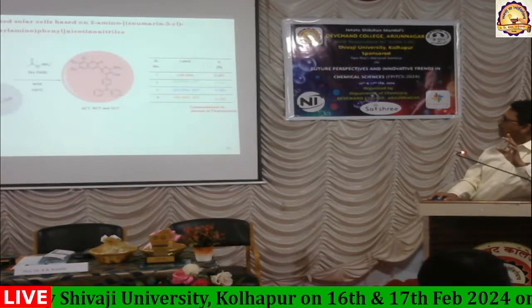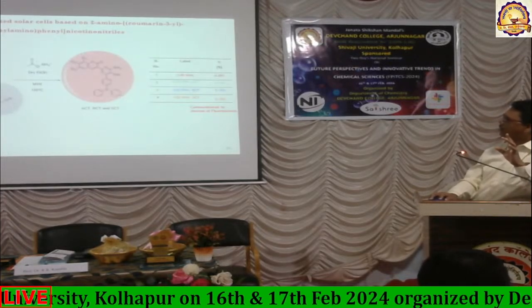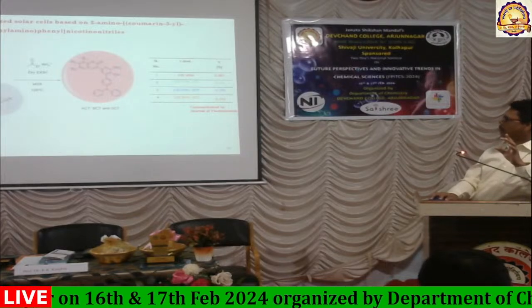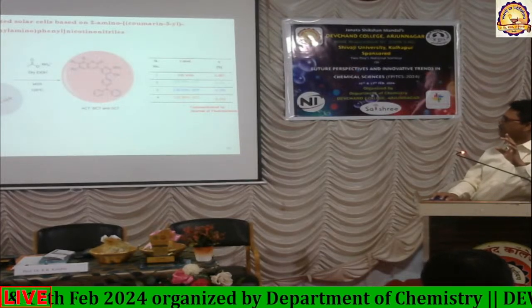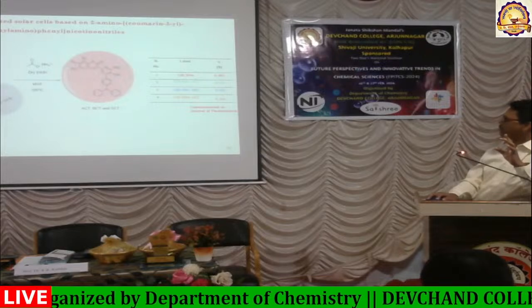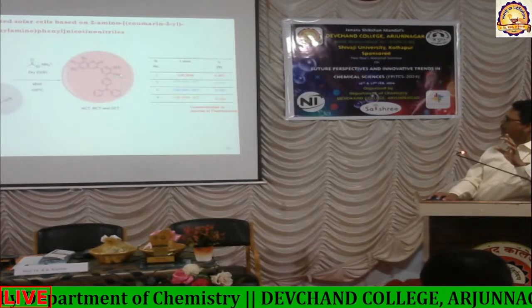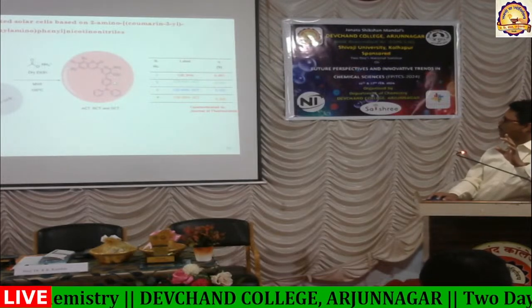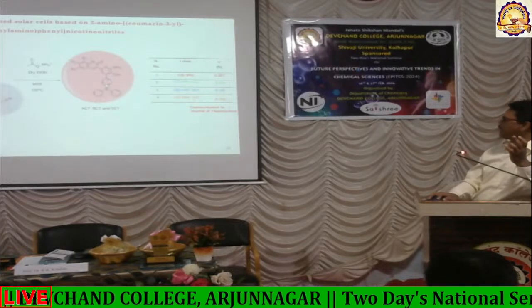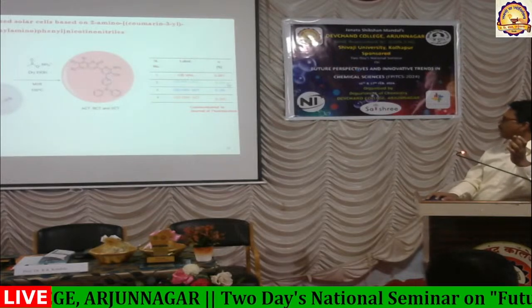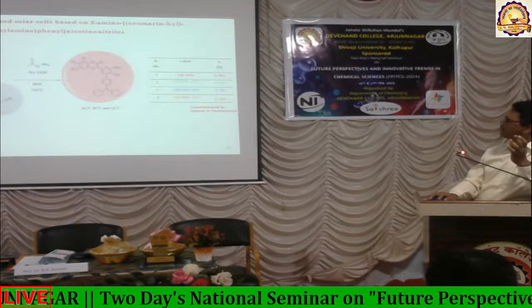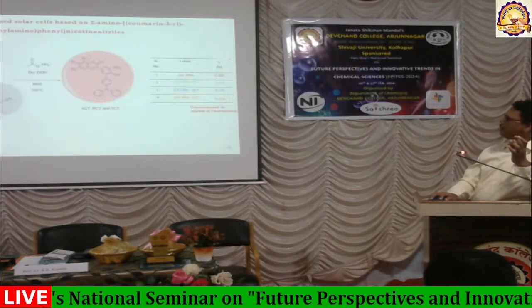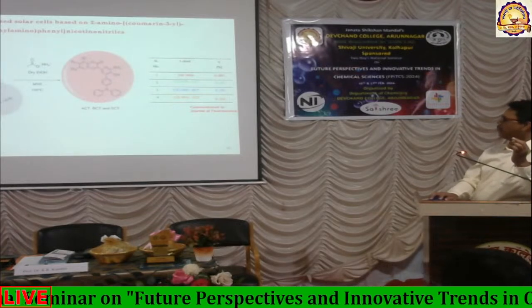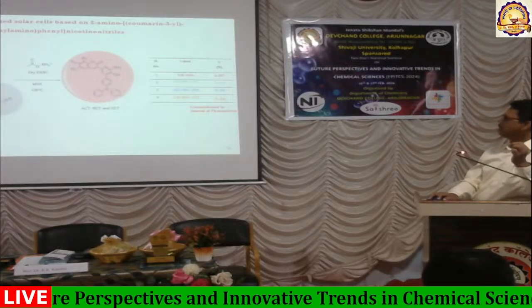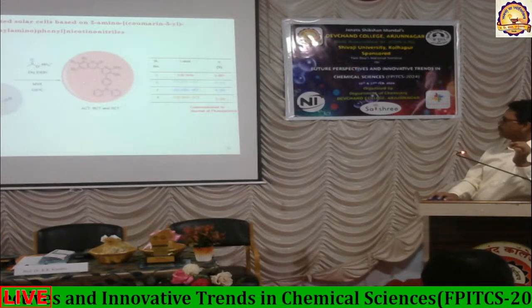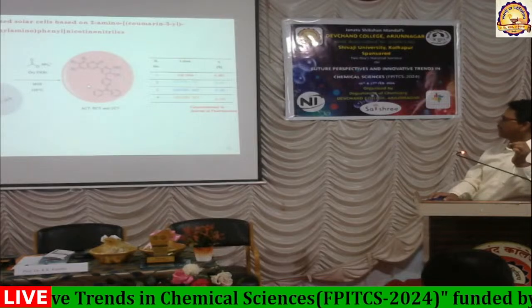These are highly fluorescent molecules that we got from a 3 component reaction, where this nitrile and this NH2 act as a linker on the semiconductor, and we used CdS nanowires once again. We got very good efficiency with these molecules, where a very simple strategy of a 3 component reaction was used to get these dye sensitizers.